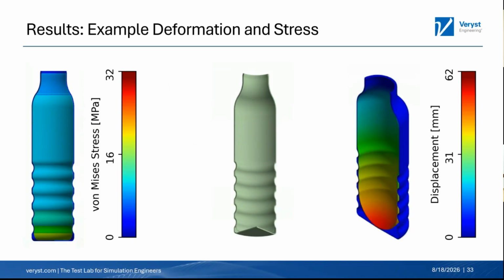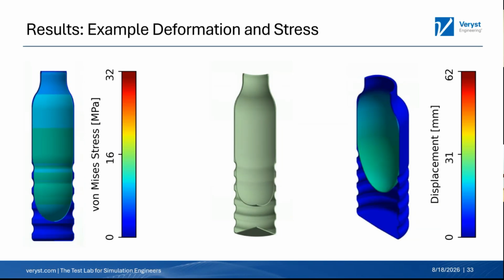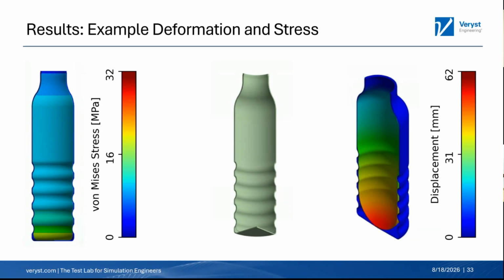So here are some animations from the simulations where we're going to let this run a couple times. Over on the left, you can see the stress in the bottle. We get a lot of stress down at the bottom because we've deformed it significantly. Over on the right, you can see the displacement where we're going for 62 total millimeters of displacement. It's a very large displacement model going on there. And you can see that the simulation actually has two components. There's the blank in the bottle that we have, and then there's actually a mold that this is being compressed to, right? That's what gives it that final shape. So this is the simulation that I ran with that material model that we talked about based on the test data for the PET.